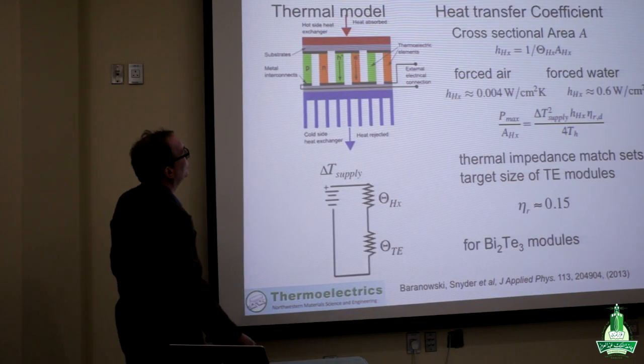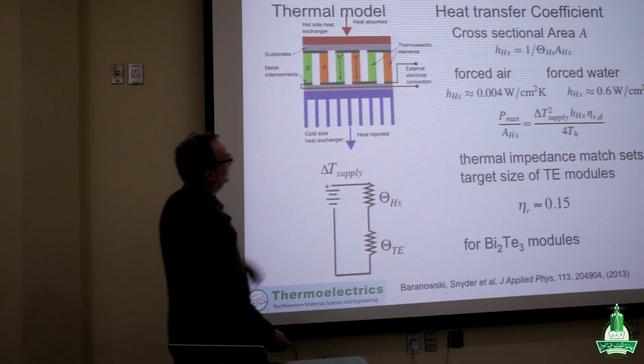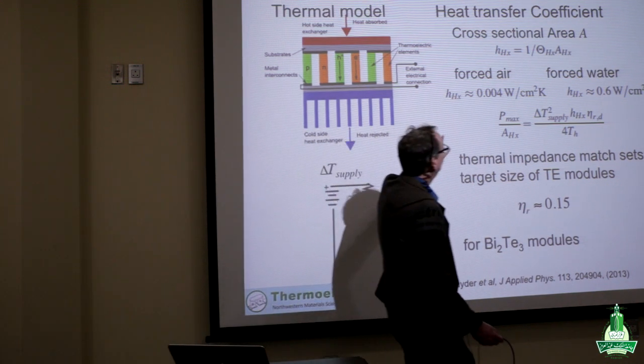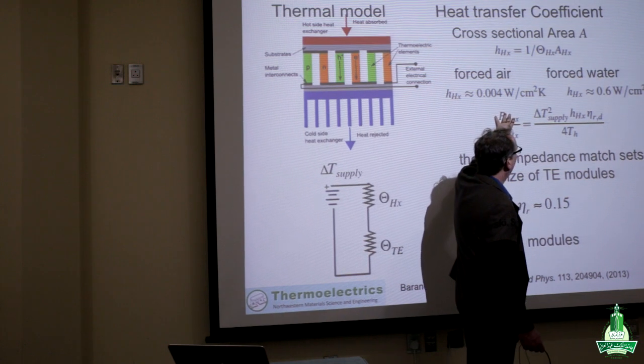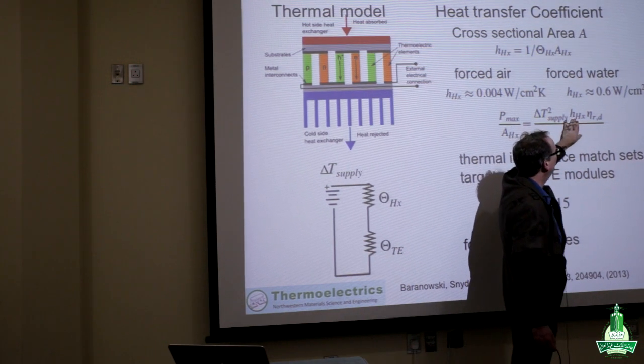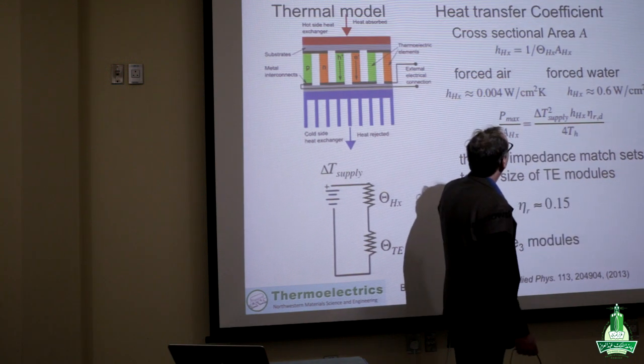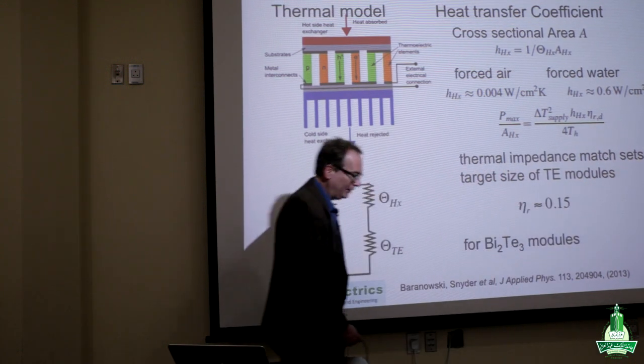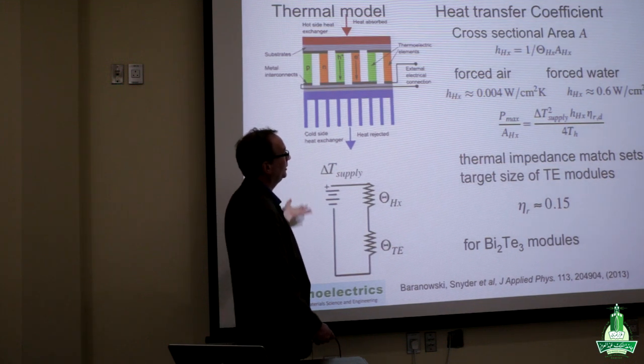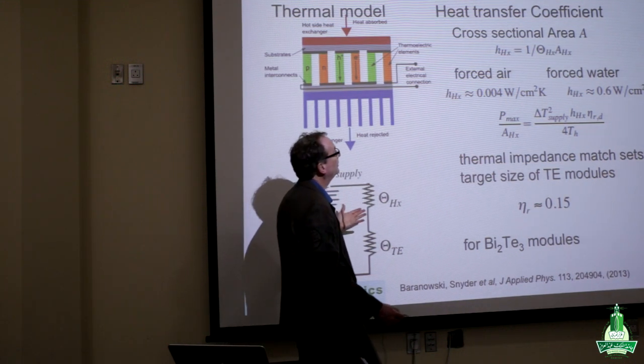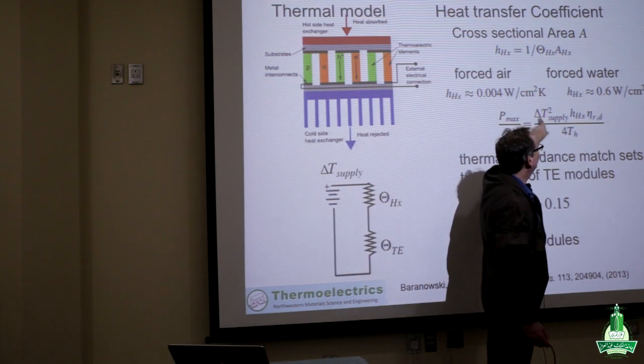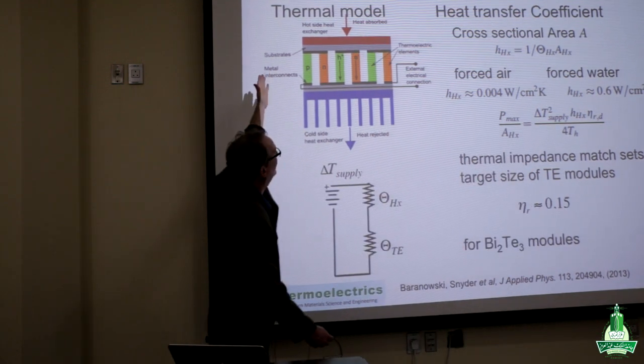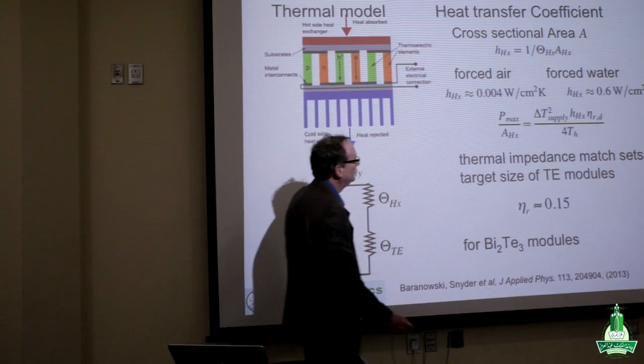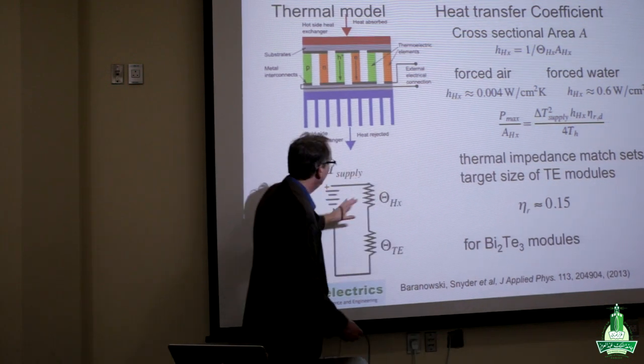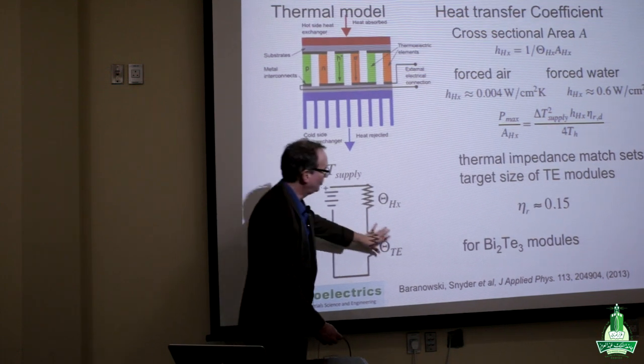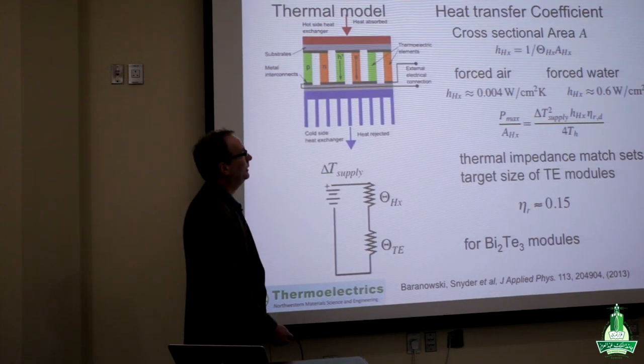Okay, so for our power then, we had a simple estimate of how much electrical power, which is going to depend on our heat exchanger parameter and our efficiency. And that allows us to get a pretty good estimate for how much power we will get out of a thermoelectric system. So for example, given the supply temperature between the very hot side and the cold side of the system, we can assume that we're only going to get about half of that delta T across the thermoelectric in the most optimized system.